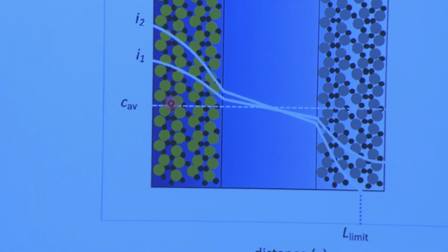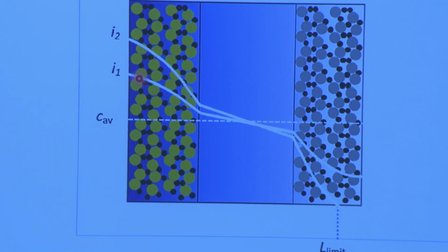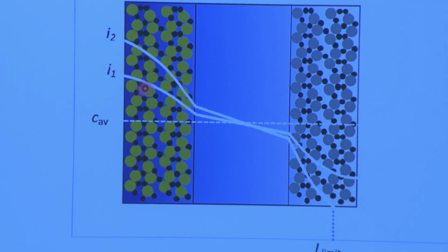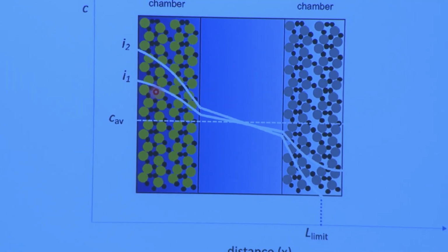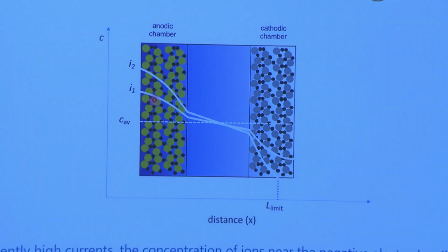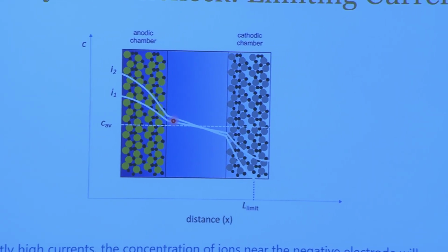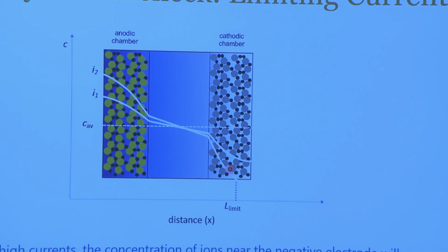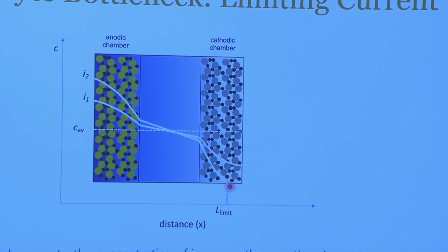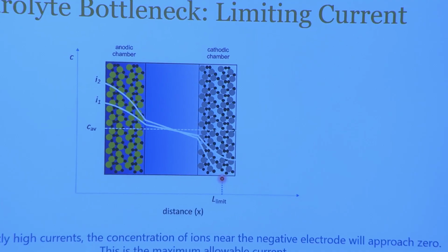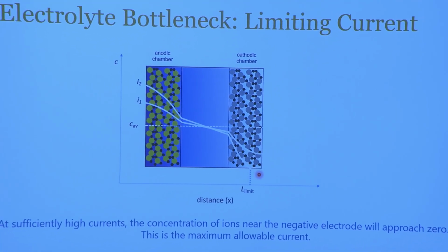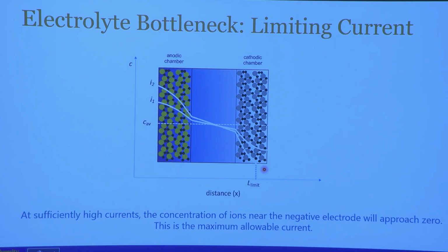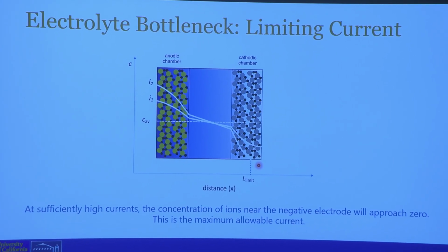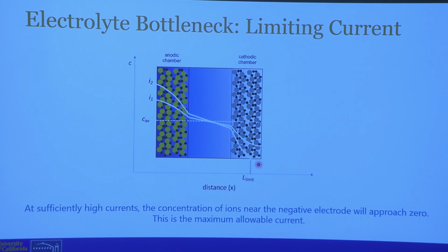Of course, if you're not using the battery, you have some ion concentration C average. And if you apply a current, I1, let's say, which is small, you'll get concentration gradients. It's a little bit like a gas flow through a membrane, and it's just a mass transport problem. But if you drive the current high enough, what you'll find is that the concentration on the other side would start approaching 0. For example, if at this point, at this current density, this third of the electrode is not being used because there are no ions. And you can easily drive your current to a point where you don't use most of your electrode.